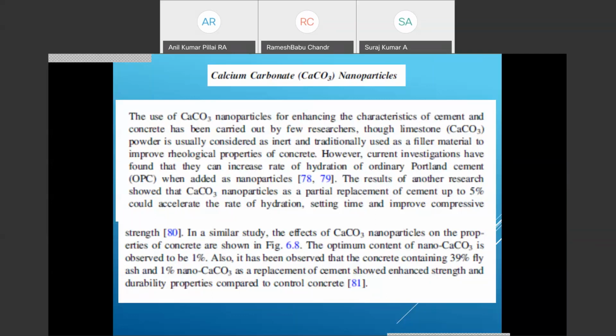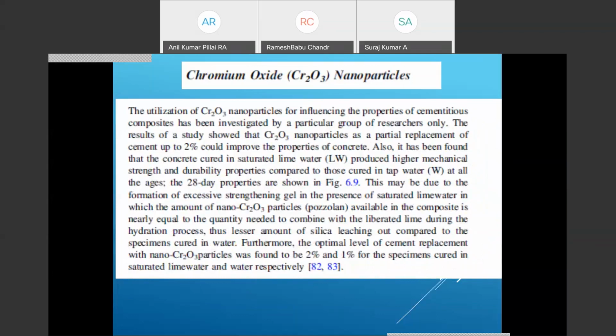As I told you earlier, nanoparticles could be used within a range of 2% whenever you want nano concrete or self-compacting nano concrete, and you can also use fly ash along with the nanoparticles. Chromium oxide nanoparticles improve properties of concrete. It has been found that when cured in saturated lime water, it produces higher mechanical strength and durability properties when compared to tap water at all ages. If curing is done with saturated lime water, chromium oxide nanoparticles produce concrete with good mechanical strength and higher durability.